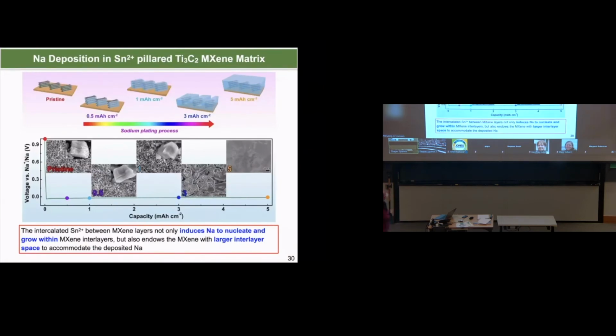Okay. So just to show you, the SEM image shows that this is the MXene-based material, and eventually we reach a very flat sodium plating process without any dendrite or mossy sodium formation.